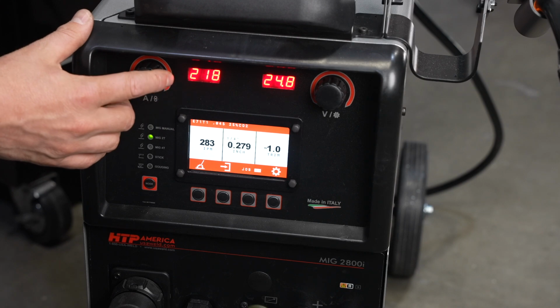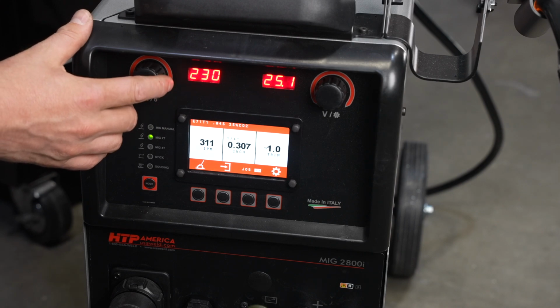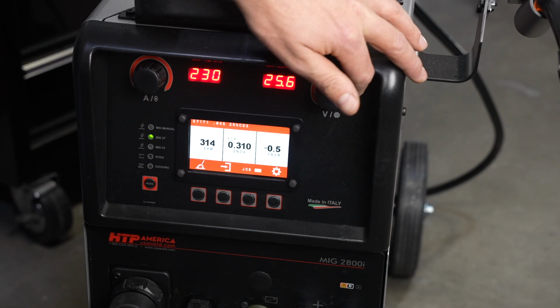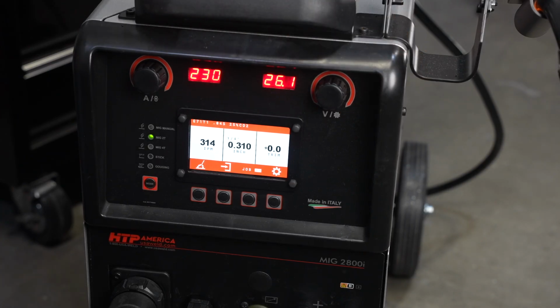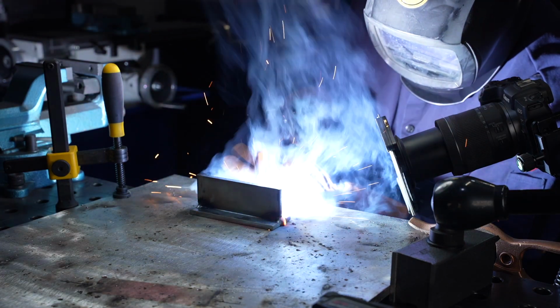So in addition to being able to run out of position like that, there are a few other advantages of running a dual shield flux core. There are also some disadvantages we'll talk about later in the video, but another one of the advantages is that you can get good penetration, or at least better weld penetration than you get with short circuit MIG. So we're going to go ahead and test that out here. Now, since I'm not running in the vertical position, I'm just going to turn up my wire speed and amperage a little bit, and also just go with the recommended voltage that they had. And these settings were kind of spot on.